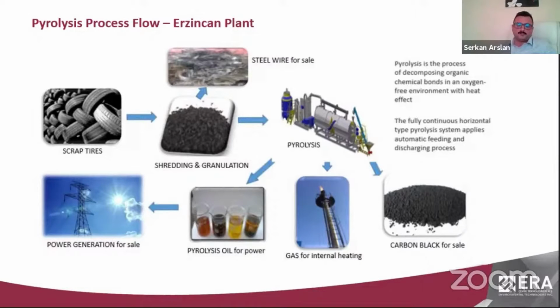Then after the cleaning processes of pyrolysis oil, we send it to the generator for electricity production. The water content of the oil is very, very important. If the water content is over 1000 ppm, we can have some problems with the generator parts. Then also we have carbon black, the char of the pyrolysis process, and this carbon black is sold to the rubber and tire producers as binding material.